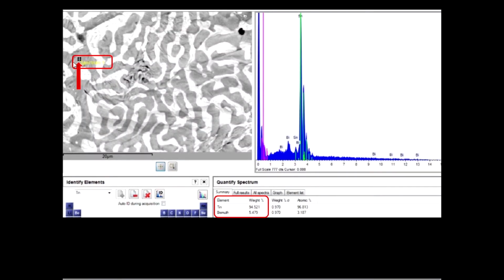Here's another one, another dark spot. Here again, you can see the weight percentage is about 94.5% tin and only about 5.5% bismuth. And there are much stronger peaks, much higher peaks for tin than there are for bismuth. The peaks are the same, just the heights are different, and that's how we get the percent composition.